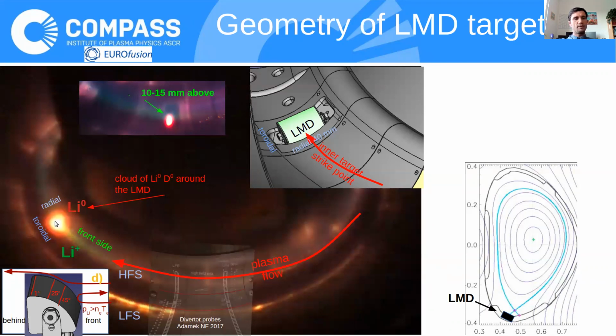Here you can see an image from the visible camera, where the vaporized and sputtered lithium radiates in red color. That's the neutral cloud. Then the lithium plus becomes green, and it's pretty nicely visible behind the target. When we insert the target not very deeply, the plasma drags the lithium behind the target, and we see some green color here.